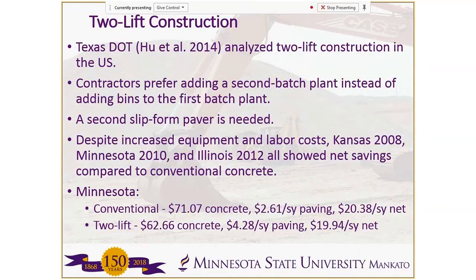Also, with the two-lift construction, as I mentioned, that's one approach that's done in Europe, and we're starting to try that out here in the U.S. As I mentioned at MnROAD, that was one of the places that we did the two-lift construction. So Texas DOT actually did a study, economic study mainly, looking at two-lift construction in the U.S. They surveyed several contractors about their process. They found that contractors would prefer to add a second batch plant, so to have a separate batch plant for the aggregates that are going to be used in the upper lift and for the RCA for the lower lift.